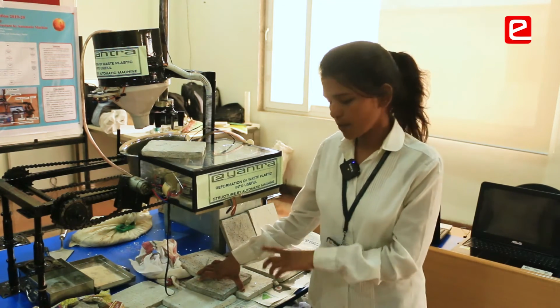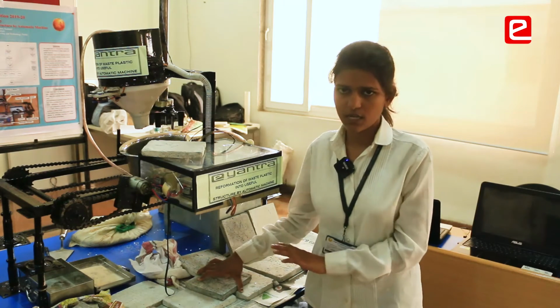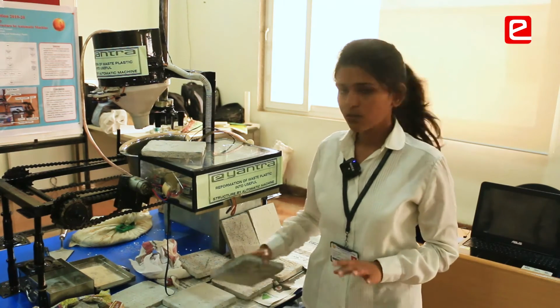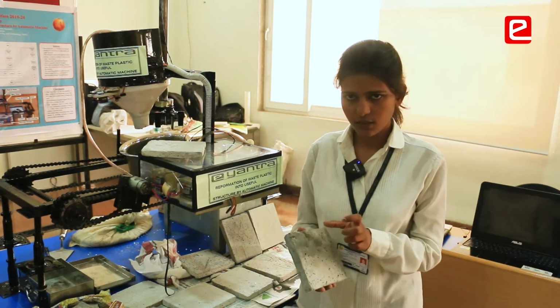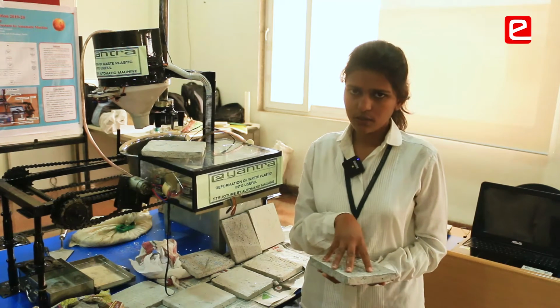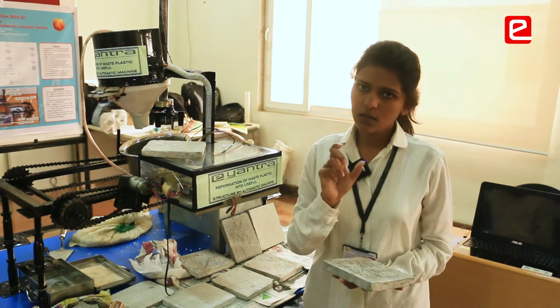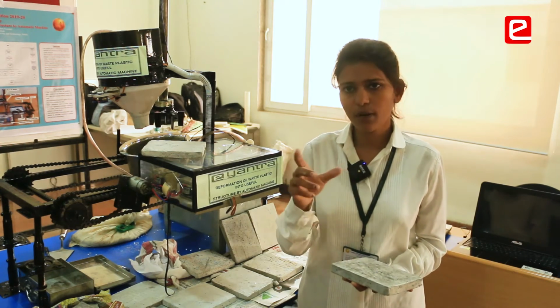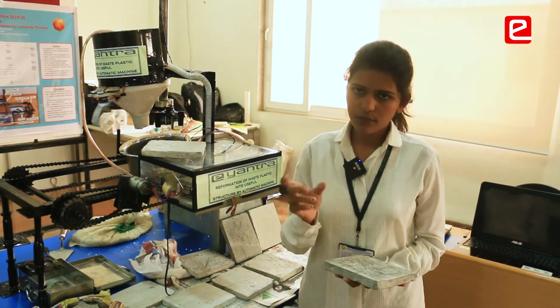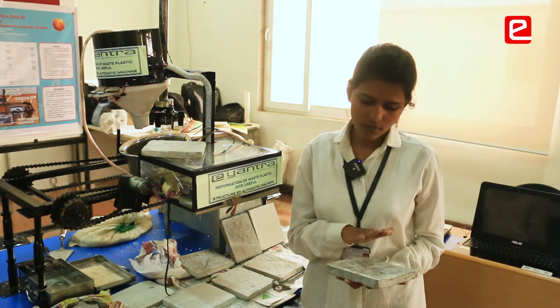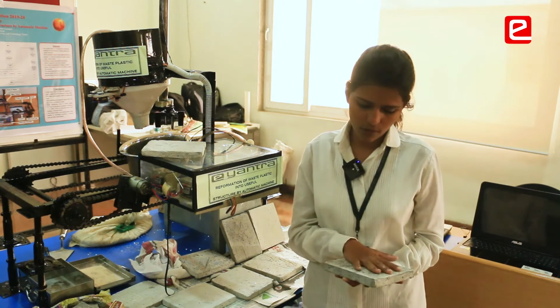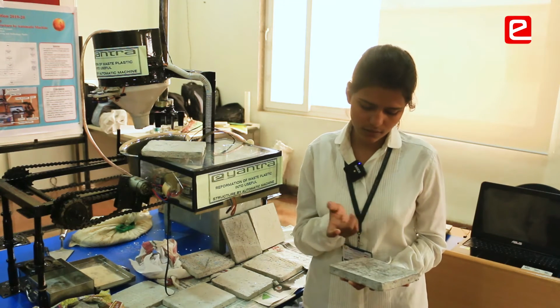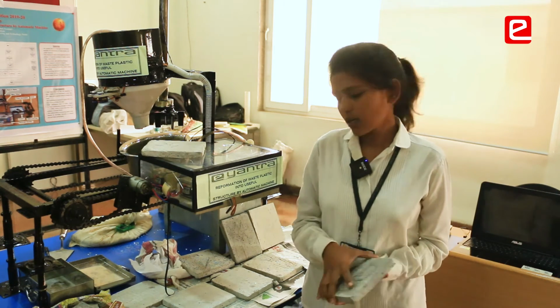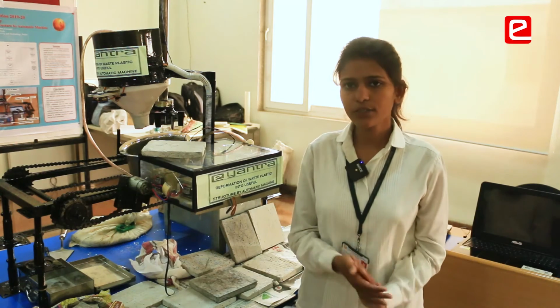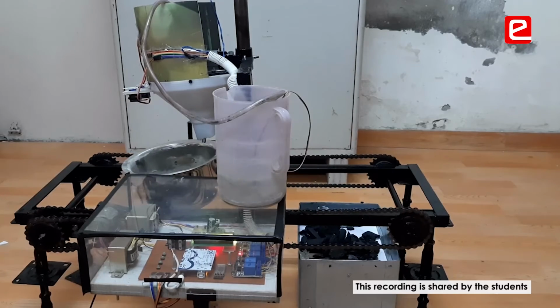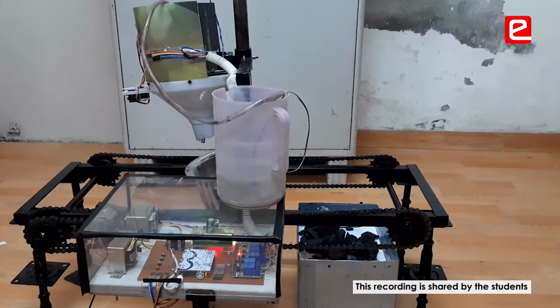After that, we test the compressive strength of this slab. We put the slab into the compressive testing machine and apply load on it. After that, we calculate the load in Newton per mm square. Through this, we compare the compressive strength of our slab to the ordinary slab. The compressive strength of our slab is 20% more than the existing slab, which is within the limit.